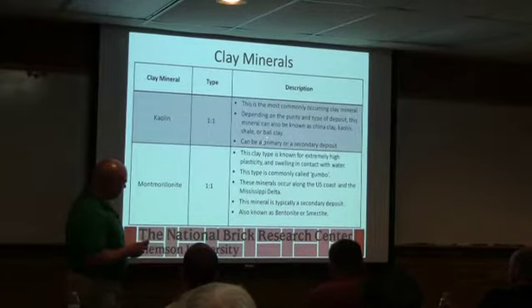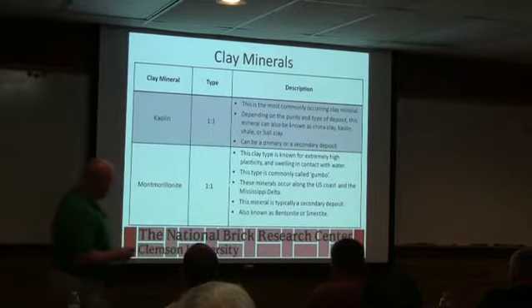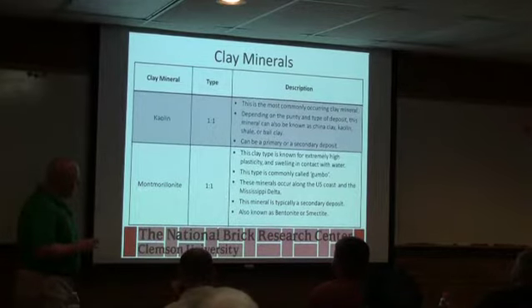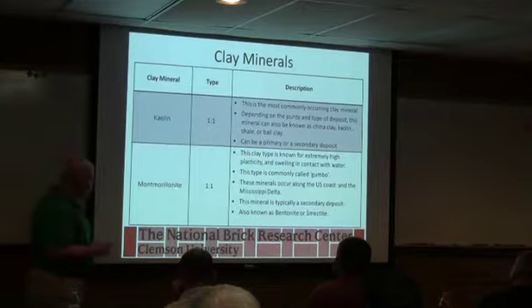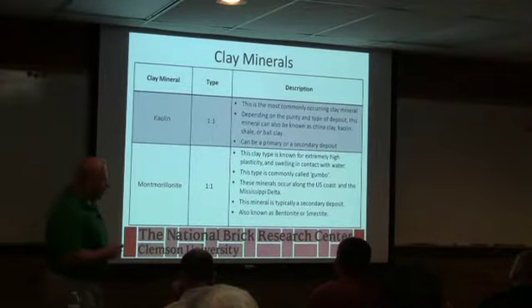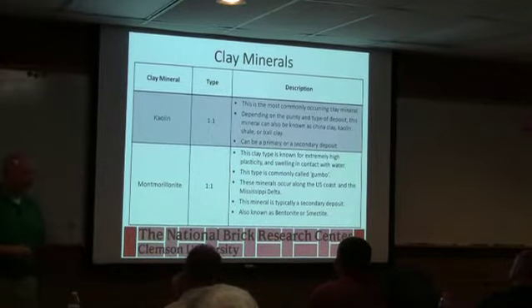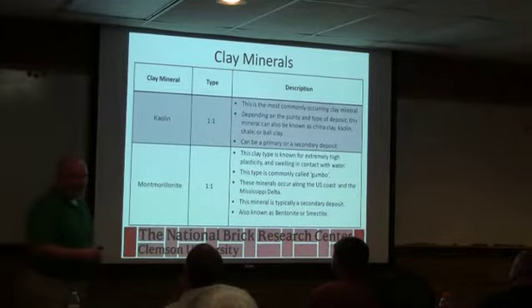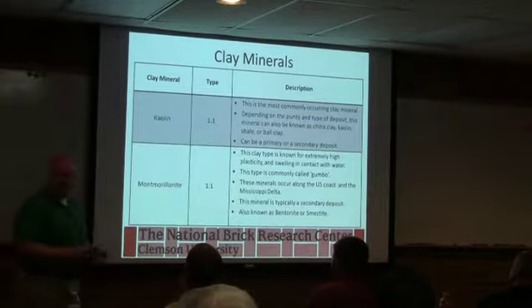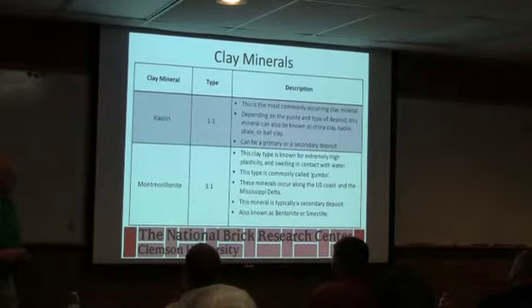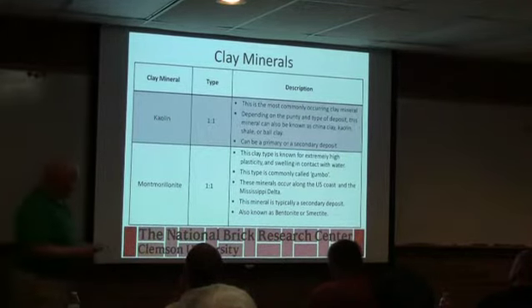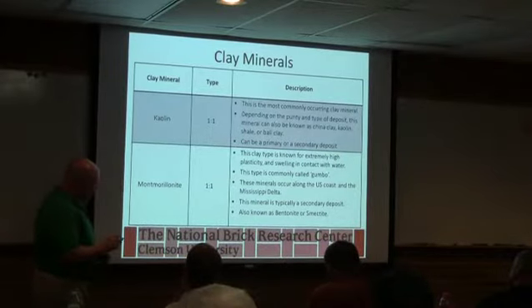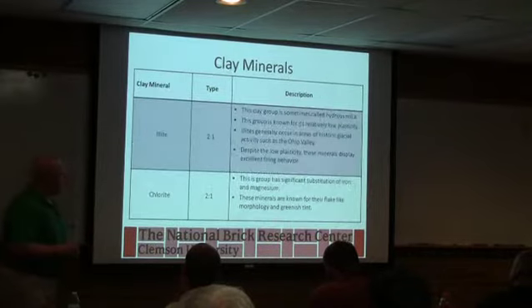of the mine. The montmorillonites, okay, those are the materials that really love water, and these can be some of the harder ones to deal with. Places that have a lot of montmorillonite, once the clay's dry, you never want to let it sit out in the air on a humid day before it goes in the kiln, because they can pick up water really fast, and they can pick up enough that it causes problems. So the montmorillonites give you great plasticity, but typically are very hard to dry.